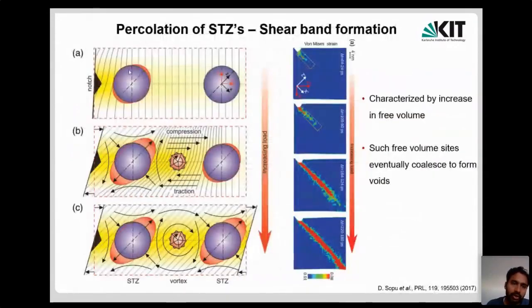And now these shear transformation zones, this is MD simulation work, because experimentally these are very hard to see. But in an MD simulation, they can be seen. In these MD simulations, you can see this big ball is a shear transformation zone. This big ball is a shear transformation zone. And when you have such shear transformation zones, they sort of rotate in some direction and propagate the deformation. These shear transformation zones combine together to form bands. In this right side image, you see some small red zones which are forming, which are the shear transformation zones, and they are combining together to form long bands. And these bands are what create the instability in the material. This instability is causing the material to shear quickly and fail.